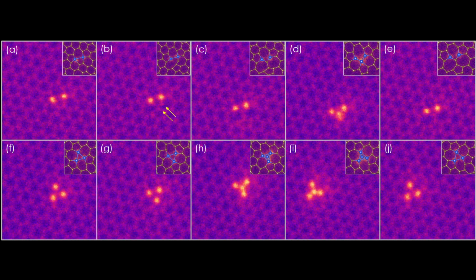In this example, we begin with this structure, but here, instead of forming it ourselves, we just happened upon it already formed. But we observed a different transformation process. Instead of healing, a bond rotation occurs in the middle of acquiring this image. These two atoms rotate by 90 degrees. According to Yang et al. in reference 37, this is a reversible process, although we only observed it rearrange once.